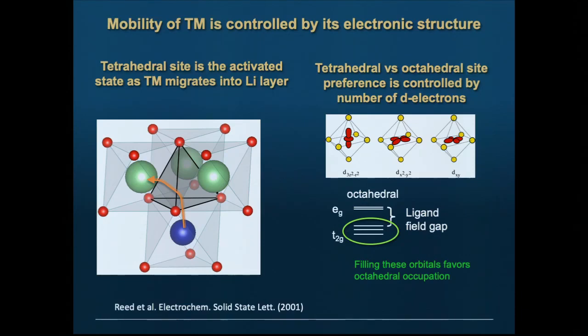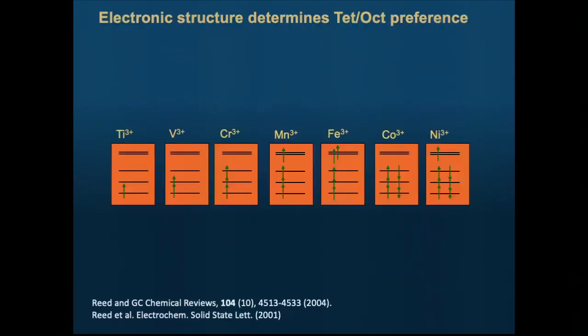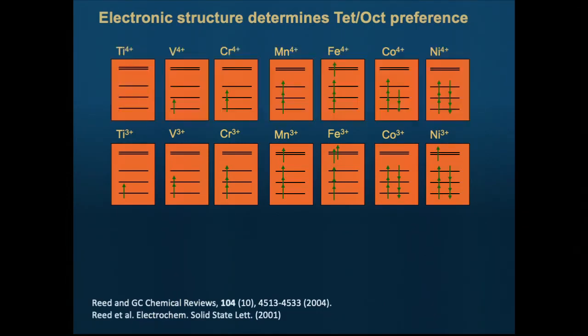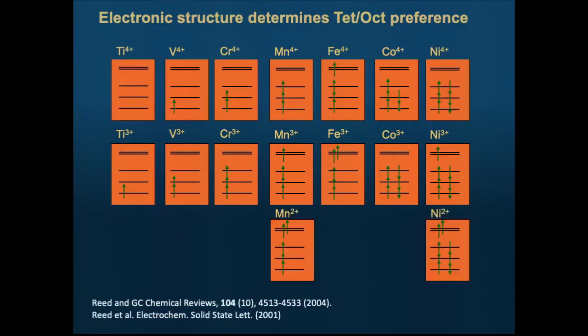Because if a transition metal has 5 d orbitals in an octahedral environment, they split 3 down, 2 up, just because of crystal symmetry. These are called the t2g orbitals. These are the eg orbitals. And this is essentially the gap created by the octahedral coordination. So in basic, simple principles, what you want to do is fill these electron states, because then you will fully prefer octahedral coordination and not fill anything else. So let's go through the periodic table now. Basically, we have 3+ or 4+ ions: 3+ in the discharge state, 4+ in the charge state. So I'll put on the 4+s, the 3+s, and in some cases, the 2+s are relevant as well.